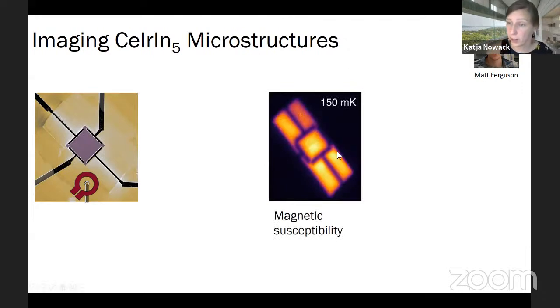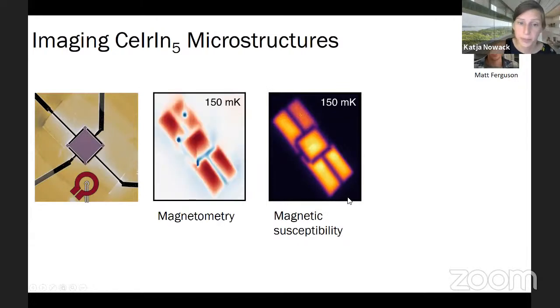And here is an image of that magnetic susceptibility, or just before I described this as the mutual inductance, but what it really measures is the magnetic susceptibility of a sample as a function of X and Y. And of course, while we take this image we modulate the current in the field coil at a fixed frequency. Of course, in DC, we also get a signal, and we simply see the Meissner effect from the sample and a few vortices being pinned in the sample.